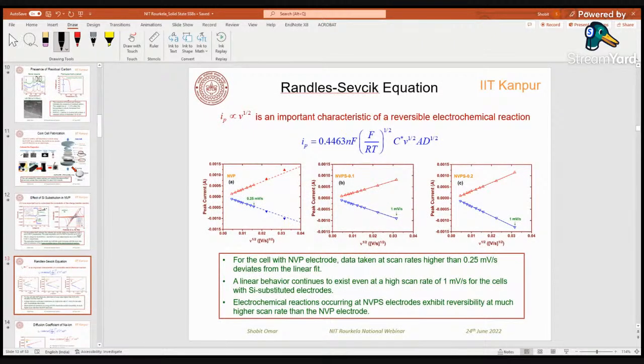Now, reversibility depends upon the scan rate at which we are doing the cyclic voltammetry. The Randles-Sevcik equation is a very important equation which relates the peak current with the scan rate. Here I have plotted the peak current as a function of the square root of scan rate, and you can see that you get a linear line. But the data point deviates from the linear fit at around 0.25 millivolt per second for the NVP case. On the other hand, for NVPS 0.1, it remained linear till 1 millivolt per second, and the same happened for NVPS 0.2. What it means is that NVP remained reversible till 0.25 millivolt per second, while the reaction in NVPS 0.1 remains reversible till 1 millivolt per second. So silicon doped NVP exhibits reversibility at a much higher scan rate compared to your NVP cathode.